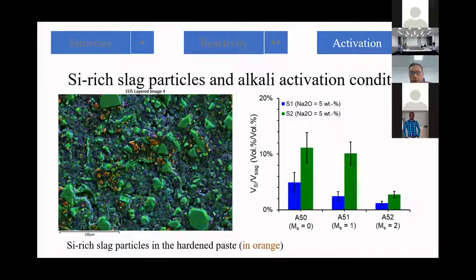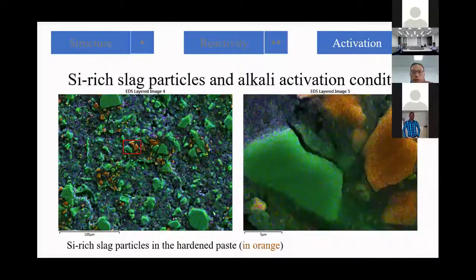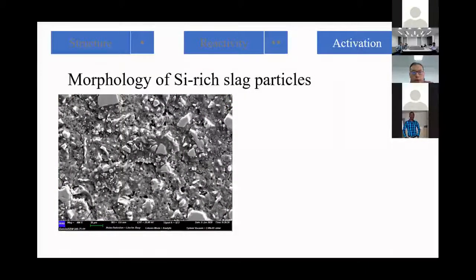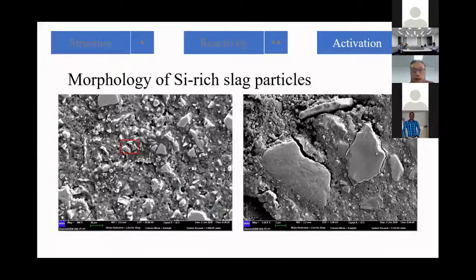And we also found a very distinct difference in the volume percentage of these silicon-rich slag particles between these two slags. So for slag S2, it always shows a higher volume percentage. And this is an enlarged image. You could see that quite a lot of silicon species deposit on top of, or on the surface of, the slag particles. We further examined secondary electron images to see the details of these particles, to see if there are visible hydration products or not.